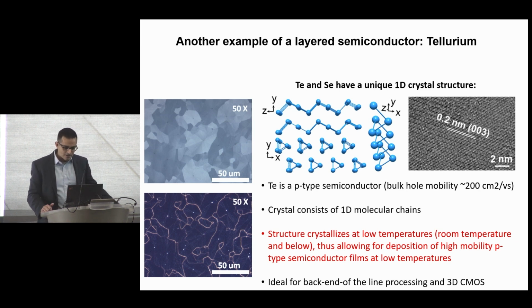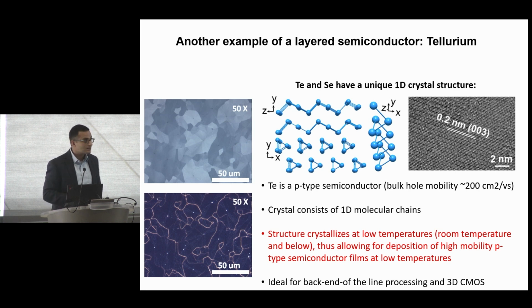Now, what's unique about tellurium is you can evaporate it at cryogenic temperatures by just using thermal evaporation, but cool down the substrate. We cool down the substrate to about 100 Kelvin, 150 Kelvin. Then we evaporate. We bring the chip back to room temperature, and it crystallizes at room temperature. So these are the results that you get for thin films of tellurium evaporated on SiO2, crystallized at room temperature.